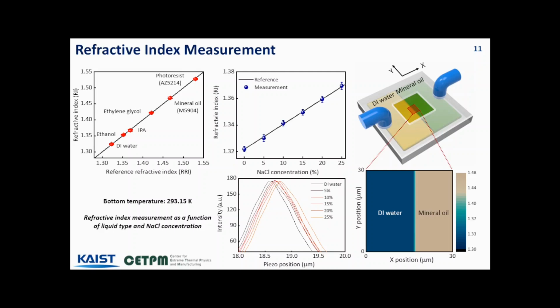Using the near-infrared interferometer, which collects data for each pixel through a CCD, we can capture the 2D distribution of liquid refractive index. For instance, we first fill the cavity with mineral oil, followed by DI water, with the injection proceeding in one direction from left to right. This sequential filling forms an interface between two immiscible liquids inside the cavity. The two regulators are used solely to precisely control the differential pressure. By measuring in a 30 micrometer by 30 micrometer area at the interface, we confirm that we can detect the boundary between the two immiscible liquids.